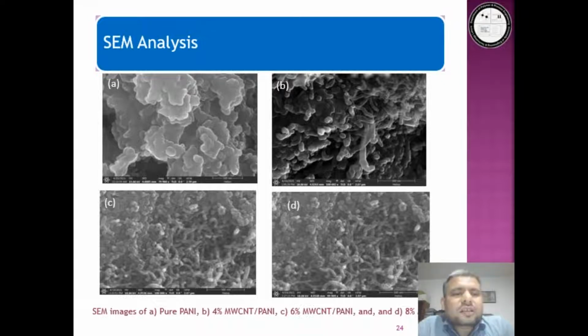Similarly, in the SEM analysis, you see in figure A the flakes of pristine PANI polymerized by in situ polymerization. It can also be seen in figure B that nanocomposites containing 4 to 8% of multi-wall carbon nanotubes show good dispersion. The dispersion of multi-wall carbon nanotubes in the composite is responsible for the better adhesion as well as continuous morphology of nanocomposites. Similarly, the good contact between constituents of the nanocomposite provides an effective path for electron flow.